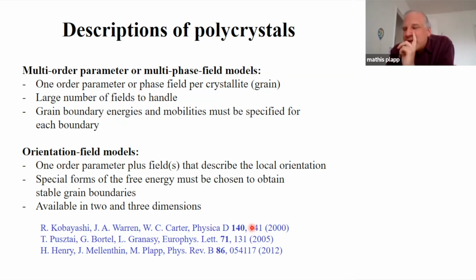Certainly feasible. It's a generalization of the multi-phase field model, but it's heavy because I need to handle a large number of fields. I also need to specify a large number of interactions between fields. So the alternative idea is to use an orientation field model. That is where I give as two variables the local crystallinity, or the local order parameter of my material, and as a second variable the local orientation of the unit cell.